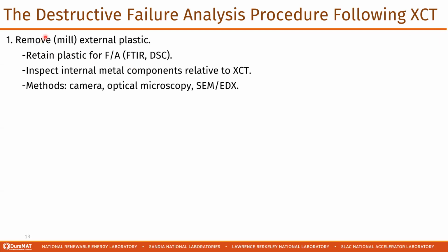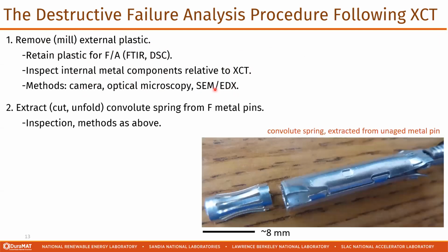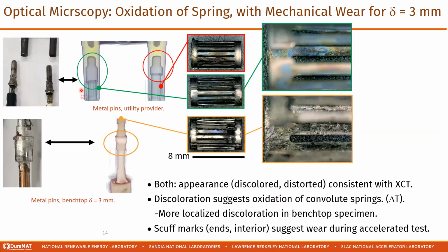So here, the first step would be to remove, meaning to mill away, the external plastic. We can retain that plastic, like for polymer failure analysis. But really our goal here is to inspect the metal components relative to the XCT imaging. And then we can come in with a camera microscope, SEM-EDX, and look at things like morphology and composition. Then we go back again and actually extract the convolute spring component from the female metal pin ends. The detail here is to peel away or open up so that these convolute springs can be extracted, and then reinspect these using similar methods like we've just mentioned.